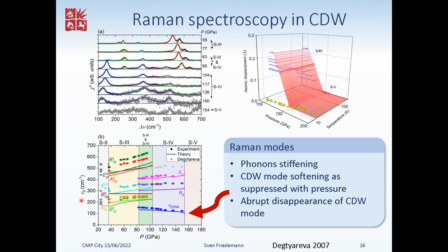In fact, I can point out this curve down here, the lowest one, is indeed beyond that phase boundary, and there's nothing left there. So the charge density wave mode is this one. You can see it's disappeared. These phonons are this mode, nothing there, and this mode, and maybe a tiny bit there. Actually, it's these two, which are both disappearing. This is a mode which originates from the pressure medium.